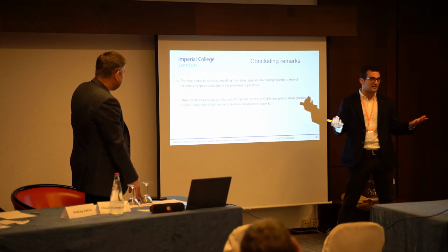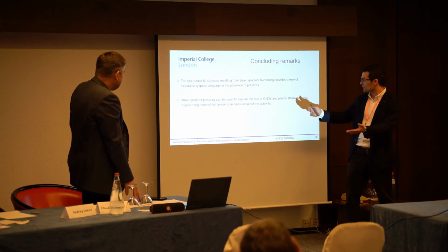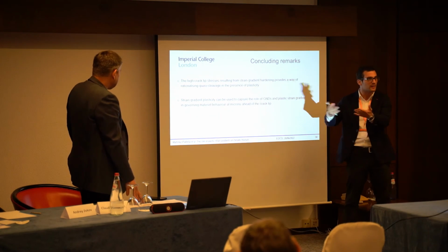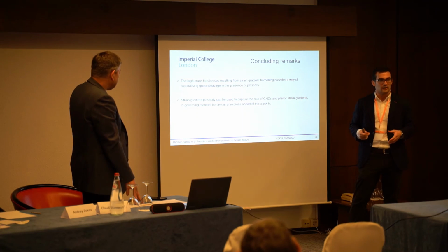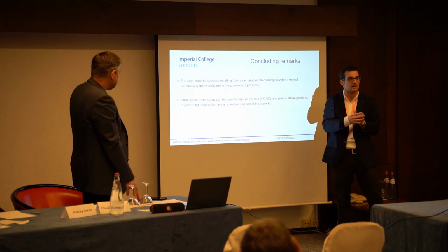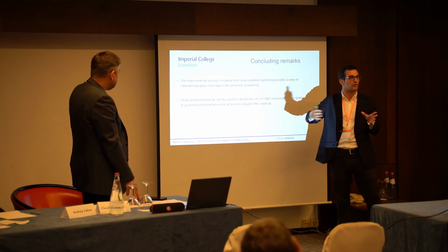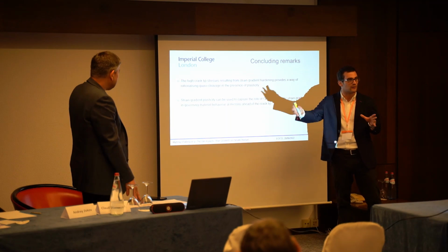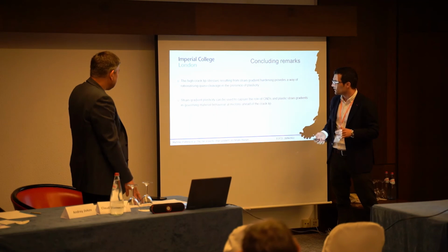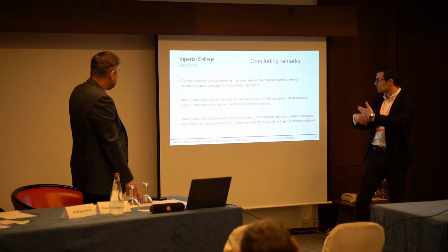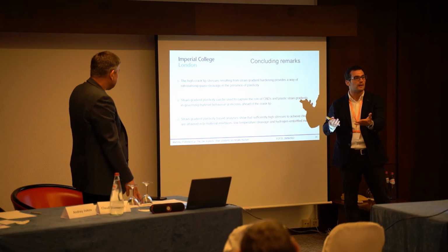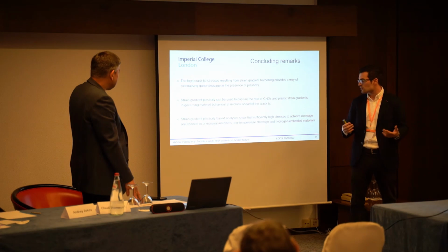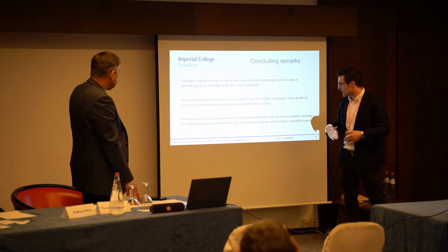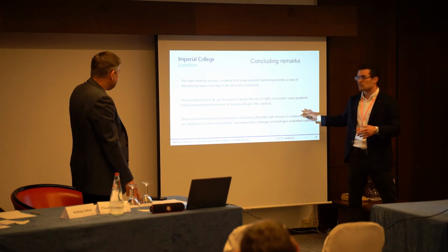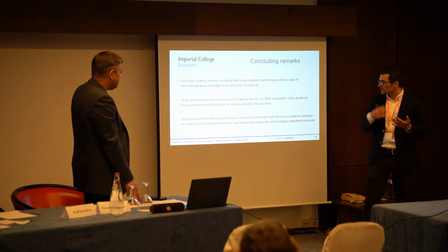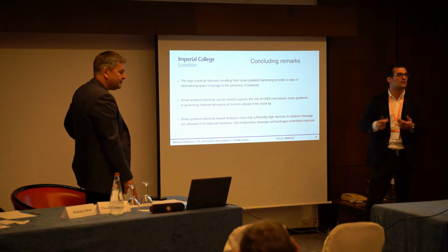We can use strain gradient plasticity to simulate those situations, to capture the role of GNDs and plastic strain gradients in governing the material behavior ahead of the crack tip. And this is particularly relevant in fracture processes where the critical distance is very close to the crack tip, as in hydrogen embrittlement, with critical distances of a few microns ahead of the crack tip. And then finally, I will say that we have done analysis to see whether we were able to rationalize quantitatively, in a mechanistic fashion, how bimaterial interfaces fracture in a brittle manner, low temperature cleavage, and hydrogen embrittled materials, and we seem to understand quantitatively what is going on using this kind of strain gradient analysis.